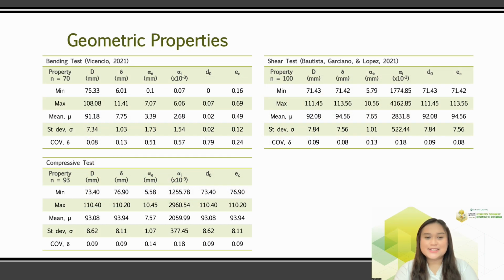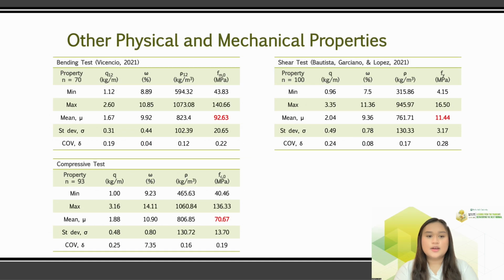The geometric properties determined for each mechanical test through measurement using a vernier caliper with 0.1% precision are listed in the tables as shown. Other physical and mechanical properties were also determined. However, it should be noted that for bending, the values were normalized at 12% moisture content. Average strengths were recorded at 92.63 MPa for bending, 70.67 MPa for compressive, and 11.44 MPa for shear strength. It could be observed that Bambusa blumeana is most resistant to bending failure and most vulnerable towards shear failure.